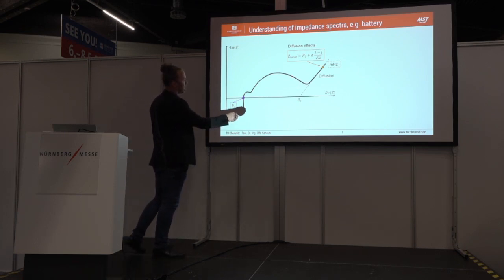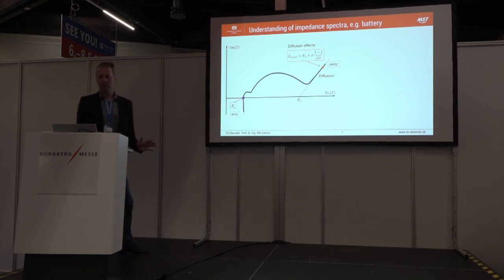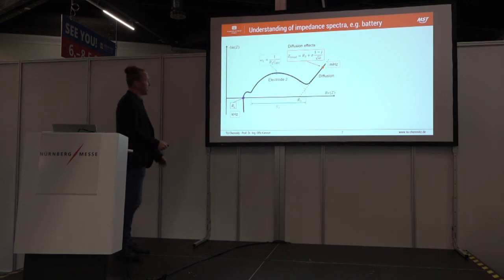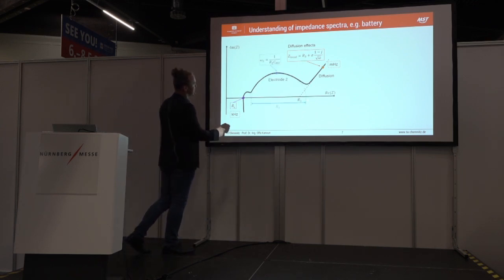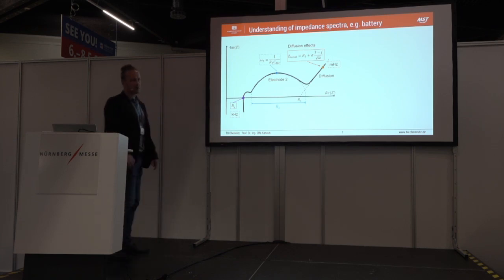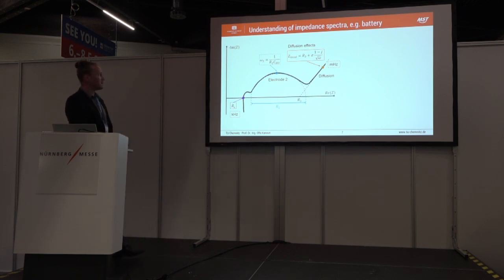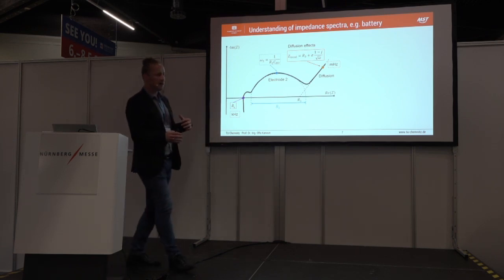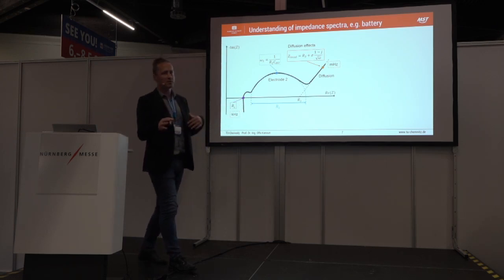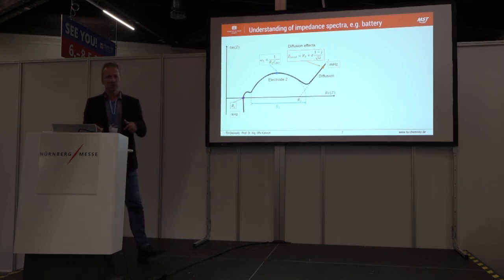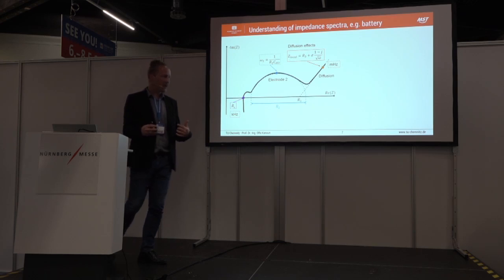And from this point, another phenomenon becomes obvious. You see here in this area there is a semicircle present, and this describes almost the characteristic of electrode 2. In this area, there is also the so-called charge transfer reaction active.